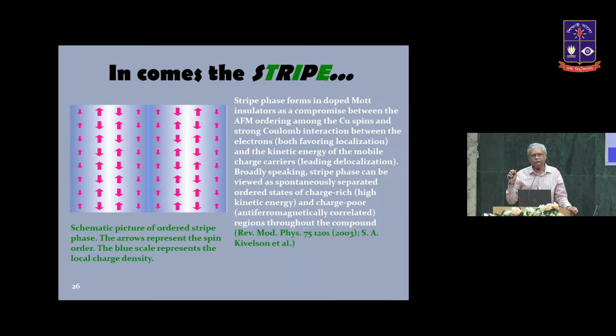And almost always when you have strong charge density wave in a system, you will see superconductivity getting suppressed. But if you have charge density wave, you must have, well, must is a strong word, but you expect a very large coupling between the lattice degrees of freedom and electronic degrees of freedom. And that would lead to a very high isotope effect. So the large isotope effect and large electron phonon coupling constant we see in the underdoped region, where the superconducting TC is low, is actually not directly related with superconductivity, but is related with charge density order or spin density order. So that was our understanding.